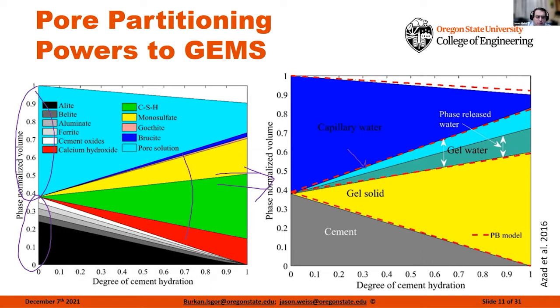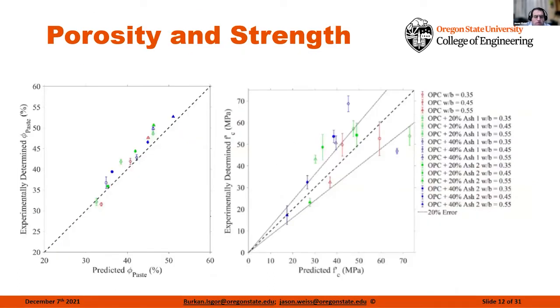We're going to be putting in Portland limestone cements. We're going to be putting in fly ashes. We're going to be putting in slags. We're going to be putting in reclaimed or harvested ashes. The value of the thermodynamic modeling is we can bring in any of those materials and run millions and millions of simulations. And when we do that, we're able to start to compare, for example, our predicted porosity versus experimentally measured porosity. And what you'll notice here is they fall very close to a one-to-one line, which means that there's incredibly good predictive capabilities using this approach.